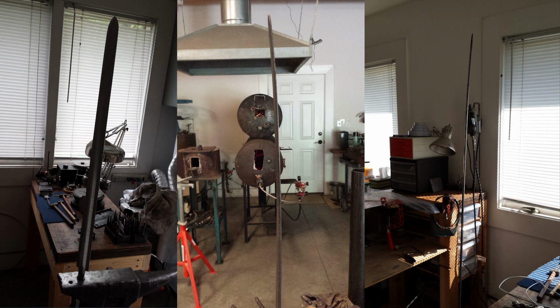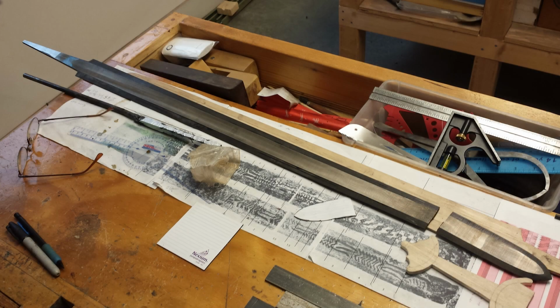As I was grinding steel away, the blade started to take a slight curvature towards the point again. I did try to straighten it in a vise, but as more steel was being removed, the curvature became more obvious, likely due to some internal tension in the crystalline structure of the steel. So it was back to the vise again. And then this happened.